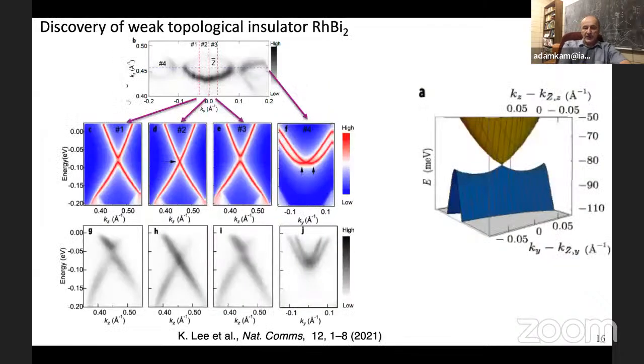Now, this material is actually even more interesting because it has a very large Van Hove singularity, which is located very close to the Fermi energy. On top here, there's a calculation. You can see 2 overlapping bands, and there's a Dirac point right here. So along one direction, this looks like a Dirac point. It's like 2 intersecting planes. Along the other direction, it looks like 2 parabolas with a minimum located here and here. And this picture on the right shows roughly the representation of the band structure, and the presence of this saddle point here is evidence for a Van Hove singularity.